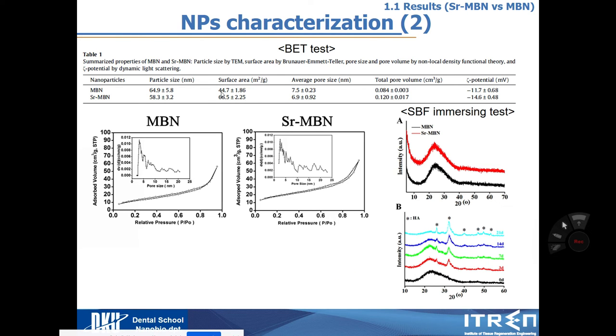And then for nanoparticle characteristics, there are many parameters to check: their size, their surface area, average pore size, total pore volume, and zeta potential. This is the charge of your nanoparticle. All of them are done by BET, another gold standard to check your nanoparticle characteristics, and these show very similar results between MBN and strontium-doped MBN.